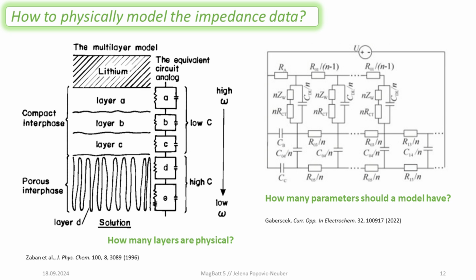And these are two extremes of these physical-chemical models that have been suggested by some great people in the field. On the left side is a sketch from one of these 90s Aurbach papers. I really love this paper because it's very, very detailed. But the model that is presented, I guess we have already left it behind in the 90s. That model shows that we have a lithium surface, and then a number of layers on top of each other, ending up with a porous layer at the end. And so the equivalent circuit is basically these layers in series.